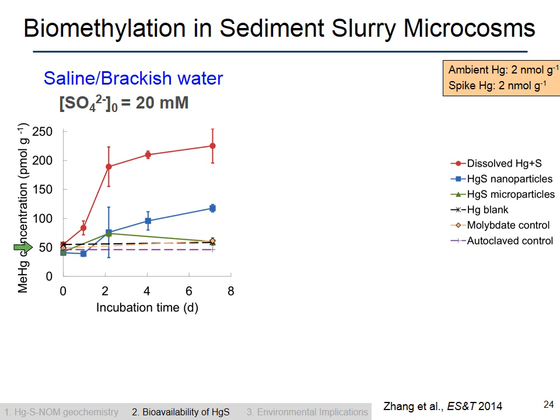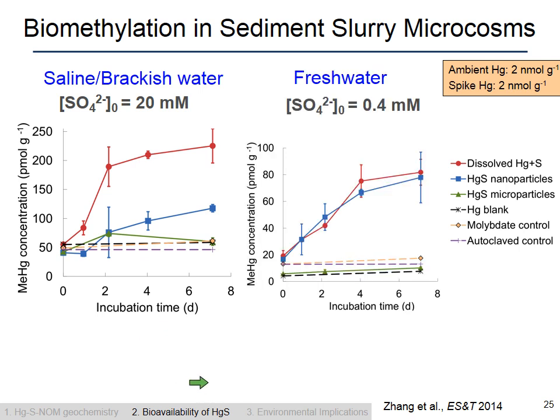And what we observed in terms of methylmercury production was a very similar result to our pure culture studies. So we see the greatest amount of methylmercury produced in those microcosms that get dissolved mercury, an intermediate amount in those microcosms getting nanoparticles, and then very little methylmercury produced in the microcosms getting microscale particles. So this is a result that is similar to the pure cultures. But when we did this in a freshwater microcosm, we don't get the same result.